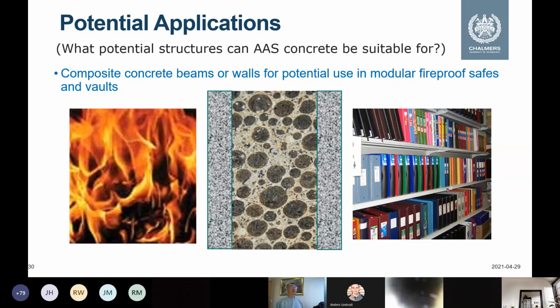Then another potential application is fire resistant walls or beams. If we can produce it as a kind of sandwich structure with strong concrete on both sides, but with fire resistant lightweight aggregates in the middle, then we can resist the fire up to 3 hours. In that case, we have the chance to save our documents. I heard that after 200 degrees, the documents will be burned. So if we have 3 hours to transfer the documents, then it should be good enough. So this is the second application.